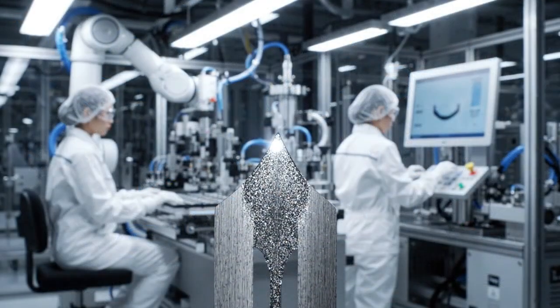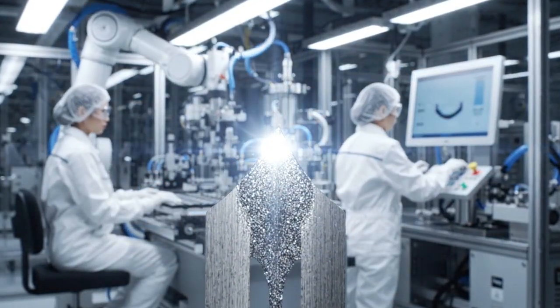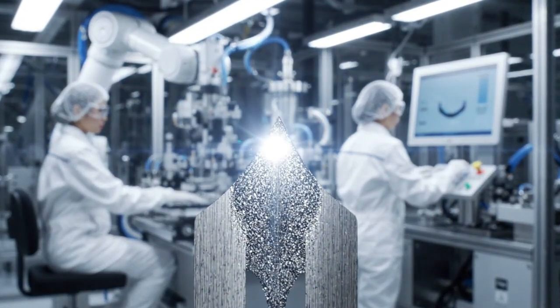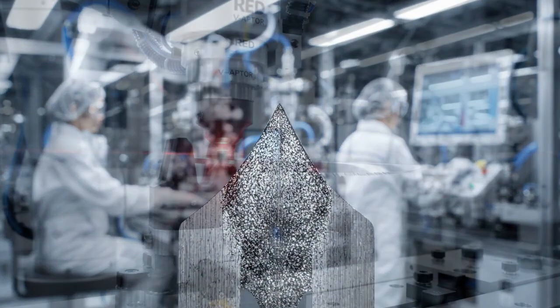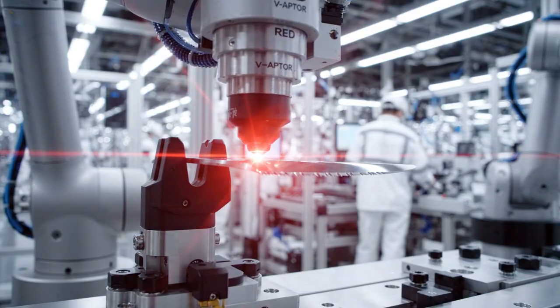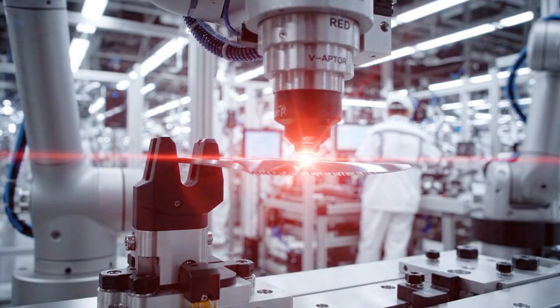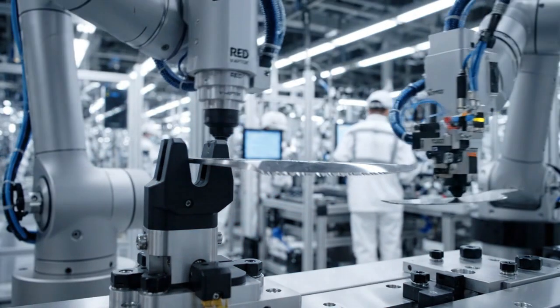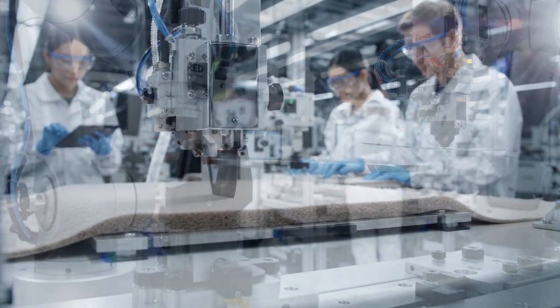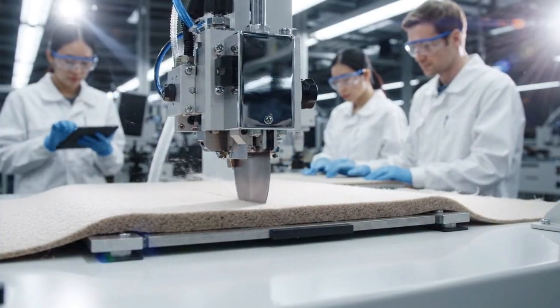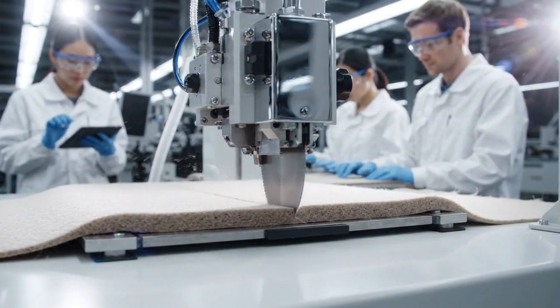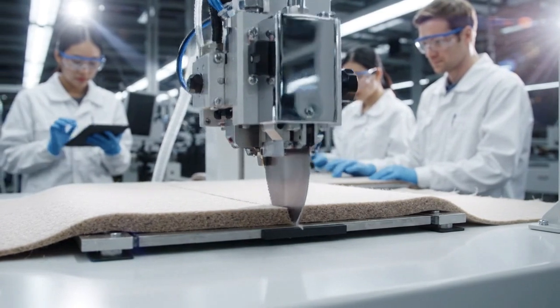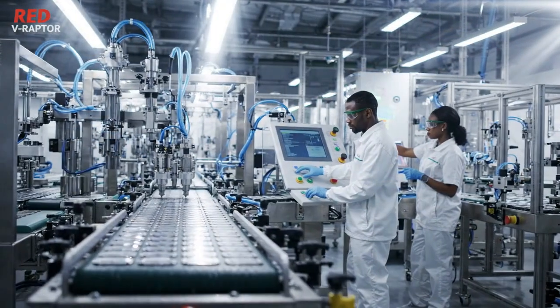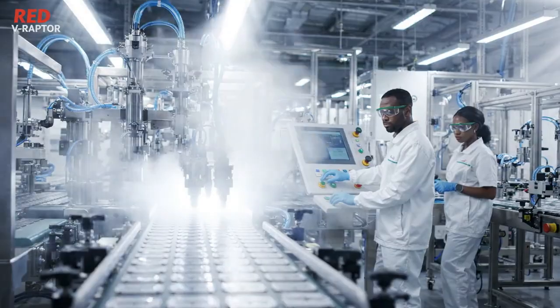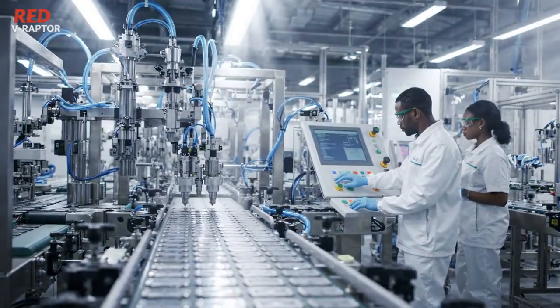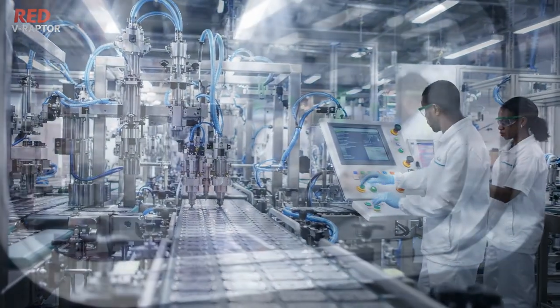Under extreme magnification, the finished edge reveals a cutting apex only 50 to 100 individual atoms wide, the definition of surgical sharpness. The wool felt cutting test provides a standardized quantitative measurement of blade sharpness, with lower cutting force indicating a sharper edge. Modern razor blades receive multiple advanced surface coatings that enhance sharpness, reduce friction, and extend edge longevity beyond what bare steel alone could achieve.